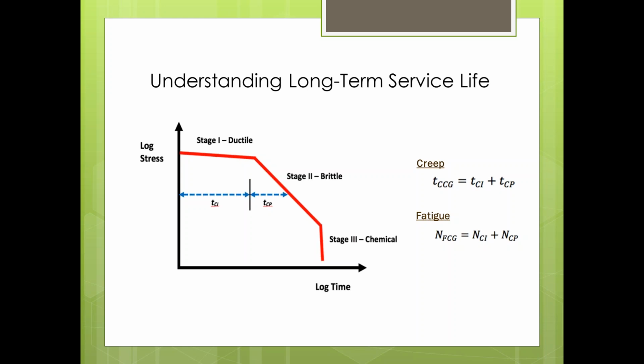It's not as common for gravity flow applications, which is really what this research is geared around here today. The only place you may see the stage one ductile failures in a gravity flow application is if you have damage during construction, where it's run over with too little cover, and the end user is placing high levels of stress on the pipe via construction loadings or handling, and you can see local tears or rips or ruptures through the pipe wall in those circumstances.